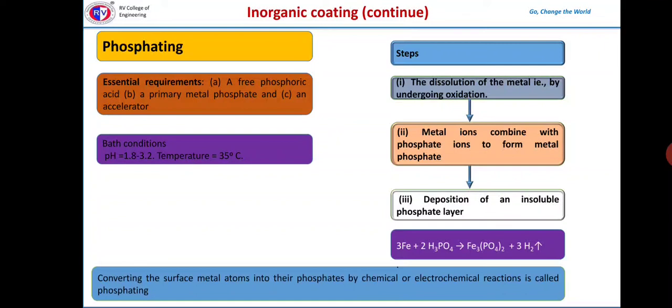This phosphating is essentially used for the production of metal parts which cannot be painted or readily plated such as nuts, bolts, or moving parts of machinery. One important application is the phosphating of galvanized iron which is otherwise difficult to paint satisfactorily.